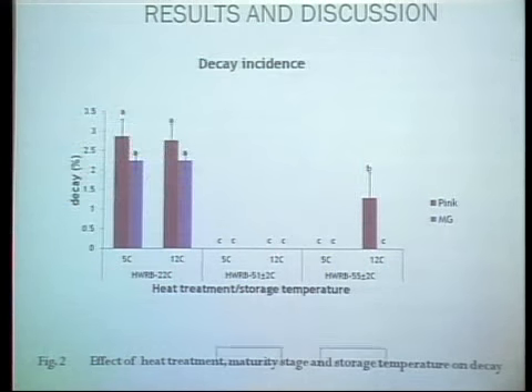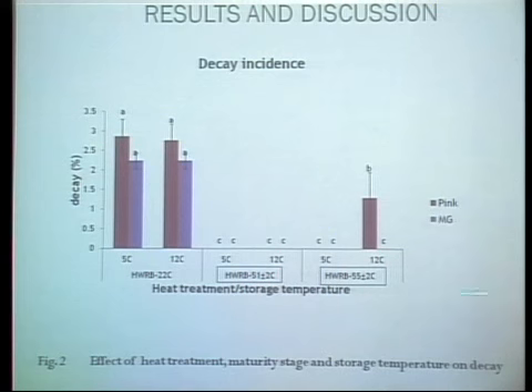So in general, we can say that these two heat treatments at 51 and at 55 significantly inhibited decay incidence. But it was more pronounced, as you can see, in 51 than in 55 for both maturity stages of the fruit.